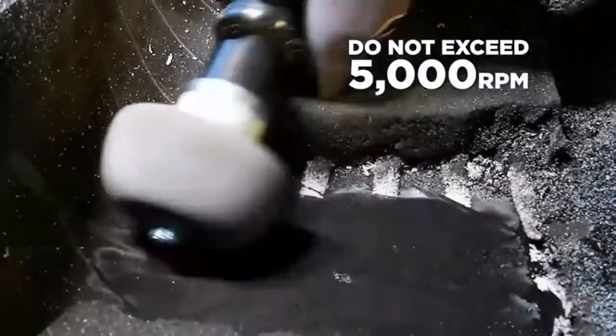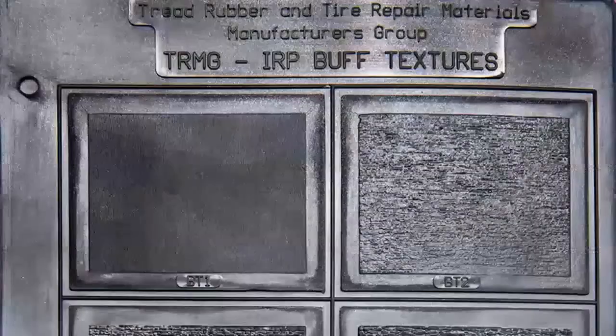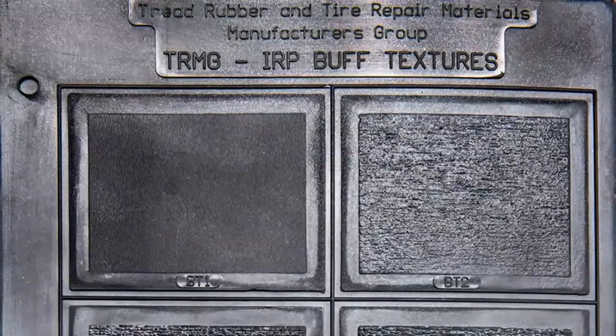Mechanically buff within the marked area using a low RPM buffer. Make sure your buffer does not exceed 5,000 RPMs. If the speed of the tool exceeds 5,000 RPMs, scorching of the rubber surface will occur, which will greatly reduce the adhesion of the repair unit to the inner liner. Also, be sure to use an appropriate buffing wheel to achieve a number 1 or number 2 buff texture. Mechanical buffing ensures proper adhesion of the repair unit to the inner liner by creating a clean textured surface.